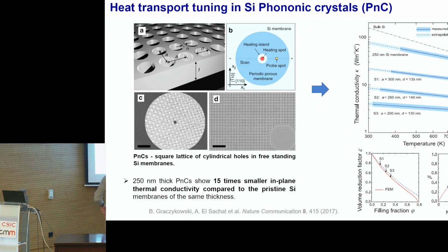Okay, good question. So in semiconductors in general, the temperature dependence follows the trend 1/T to the power of n. In silicon there's a specific number that corresponds to this factor n. The higher the factor, the stronger the temperature dependence. This is the general picture. So here you see from the bulk we have something like minus 1.31, and then we go to the 250 nanometer silicon membranes, and as we decrease the thickness, this factor is decreasing.